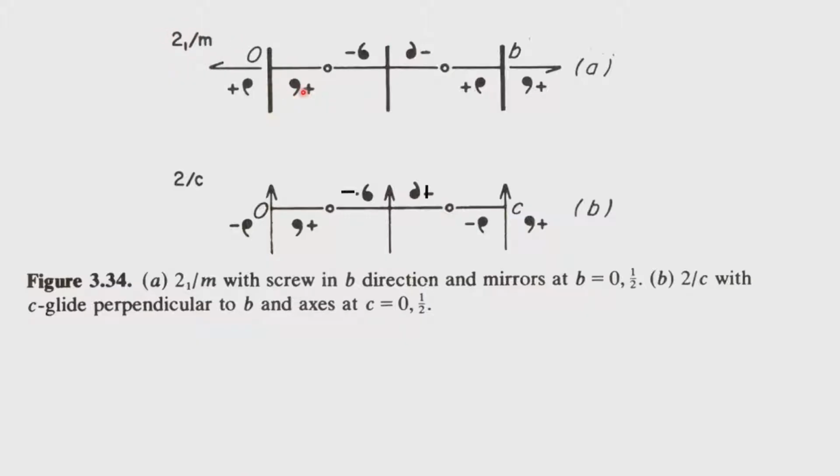Then we have x y z and this point which is the mirror symmetry, which will take us to x y bar z. So, the presence of the symmetry at x y bar z and at the origin, and the presence of the symmetry 2 1, if we keep operating again one of them or operate them together, we will not get back to x bar y bar z bar. X bar y bar z bar will not get invoked, and therefore, the space group points will not complete the definition of a group. So, mathematically, in order to complete the definition of a group, it is required that we move the center of symmetry to the origin.